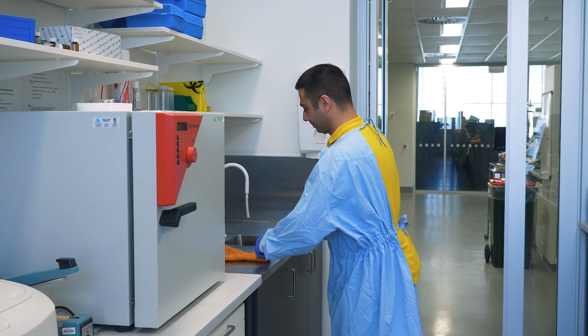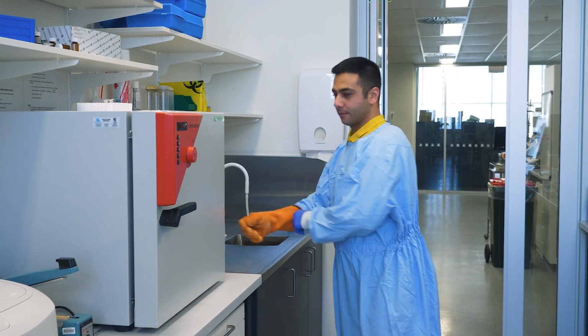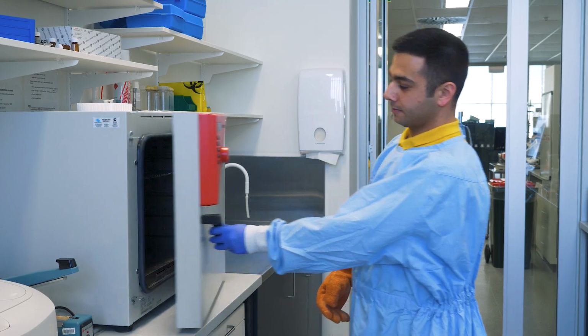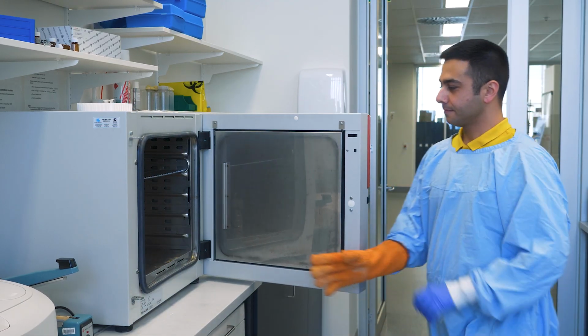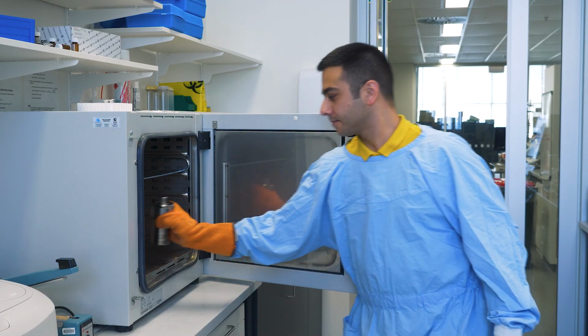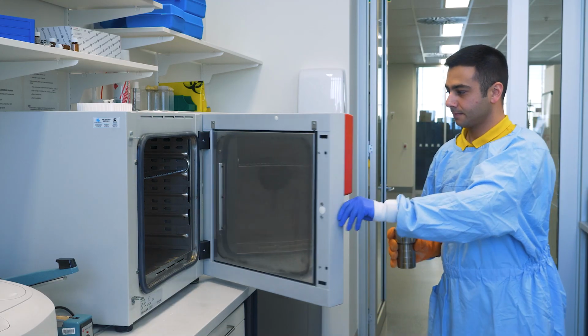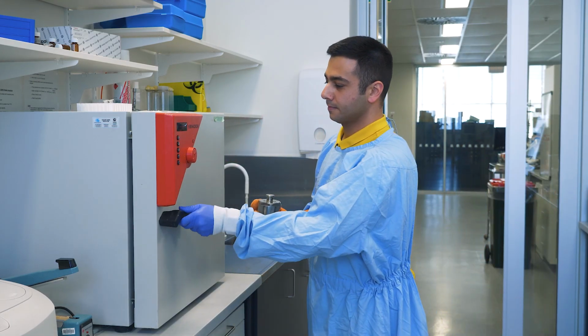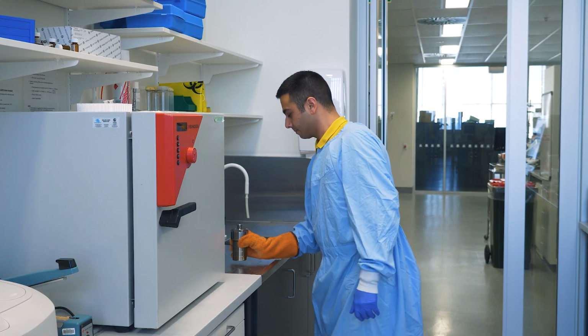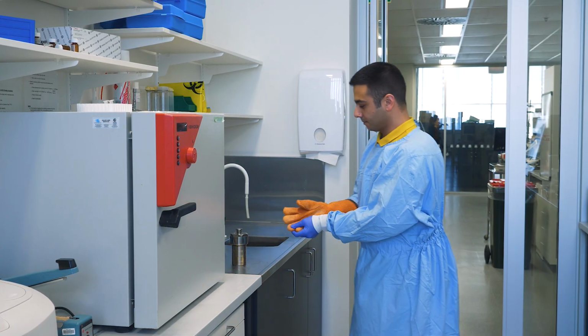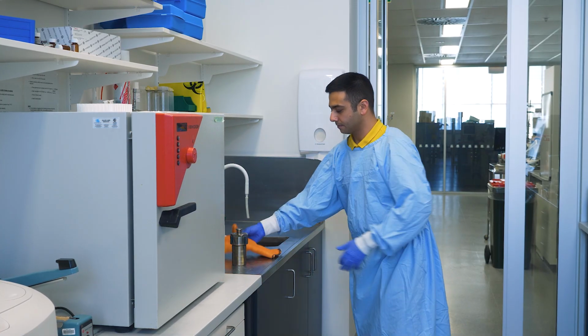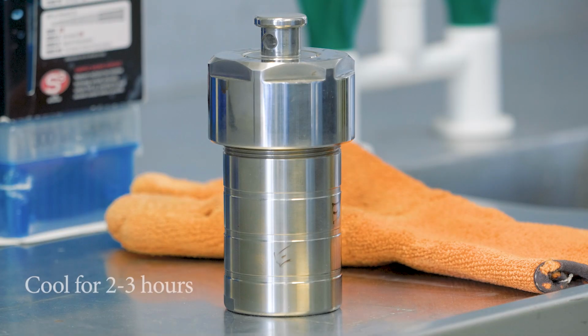Okay, now that 8 hours is up, I will go ahead and take the autoclave reactor out. I need to use thick gloves because the stainless steel shell of the reactor is very hot. We will leave it here to cool. 2-3 hours should be enough. See you soon.